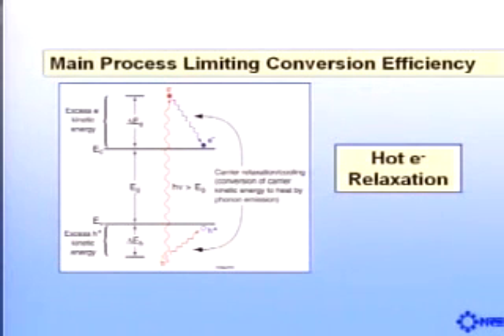And how do we achieve it? Well, first, just looking at what limits the efficiency. The major limitation is the fact that for a single bandgap absorber optimized at 1 to 1.4 eV, the solar photons ranging from 3.5 eV in the near ultraviolet to half an eV out in the near infrared result in an energy loss of the high energy photons absorbed in an optimum bandgap converter. And in the Shockley-Queisser analysis, it was assumed that this extra energy, which is in the form of kinetic energy of the electrons and holes, is converted into heat. So when you do the thermodynamics, you want to look for the conversion of the free energy of the photon into the free energy of the electricity or the chemical fuel. This is a loss, and that's how you come up with the 31%.